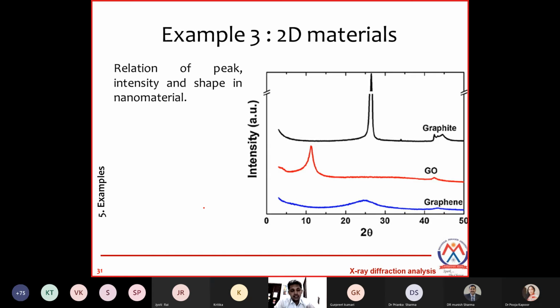So what we do, there is one intermediate stage that we call graphene oxide. The interplanar distance in graphene oxide is larger. So what we do, we take the XRD sample of graphite. Once I have taken the XRD sample of graphite, I'll start performing the experiment. Intermediately, when I come to know graphene oxide is being prepared, I'll take the XRD analysis. Now from this black line, I have reached over here because the interplanar distance is changing. So this is approximately 0.3 and this is approximately 0.9.